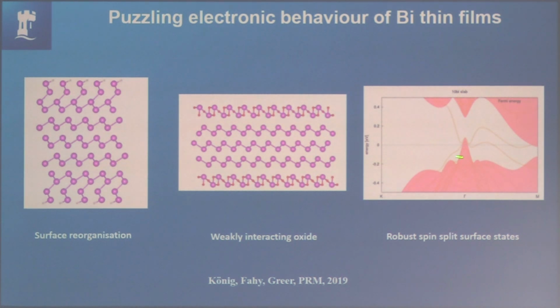So these surface states that you see here, this is the projection from the bulk density. So you know that the yellow, if you can't really see them, but the states down here, they're bulk-derived states. But these states here are 100% associated with the surface. They're there whether you put the oxide on top of them or not.